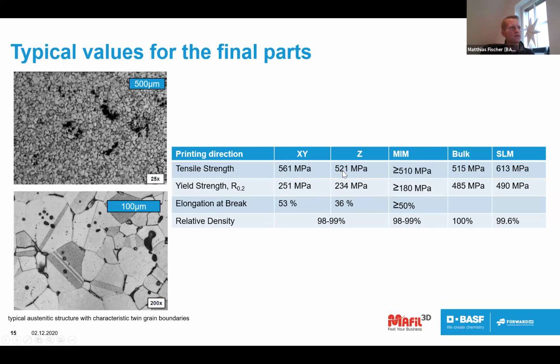Especially the elongation at break is much lower. But we are talking here about a tensile strength of about 500 megapascal, which can definitely compete with the MIM process, but also with parts printed in the SLM process. Of course, it always depends on the porosity of the part, on your print settings, and also on the post-treatment, like polishing, for example. But in general, you can expect parts which are really quite comparable concerning the mechanical properties.